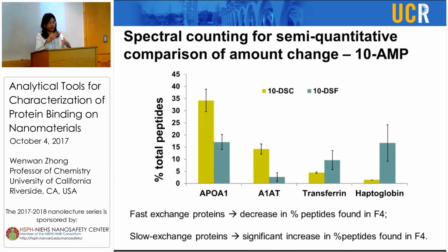When we look at the relative protein content prepared by centrifugation, which is labeled DSC, and prepared by flow field fractionation, which is labeled DSF, we could see that for the ones with a very fast exchange rate, you should see a decrease in the percent peptides found in the F4 portion, which is the blue bar. For example, A1AT and the ApoA1 protein show fast kinetics. But for transferrin and haptoglobin, we could see a higher ratio of peptides found in the F4 method. That's because the ones in the soft corona are already removed in F4, so the relative proportion of the hard corona will go up.